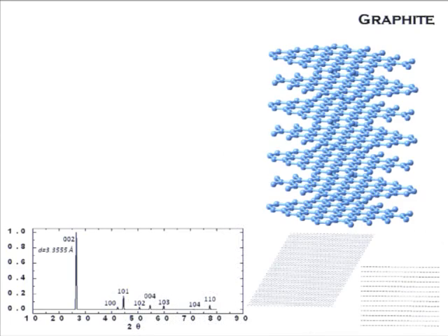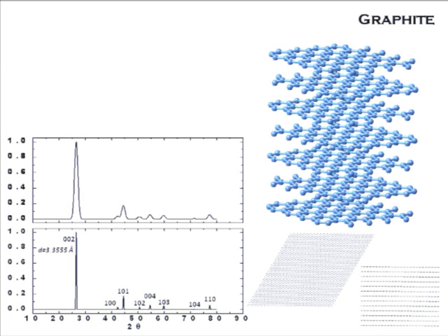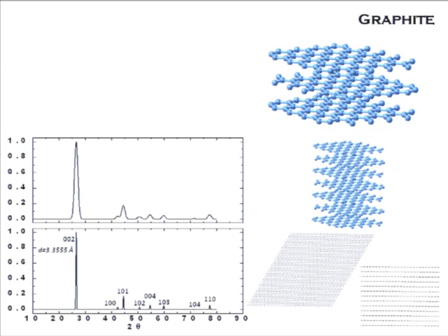And the diffraction pattern will be somewhat similar to what we had originally, but with broader peaks, and the peaks actually broadened anisotropically, which is hardly surprising, since this distance is greater than the distance perpendicular along the planes. Well, let's not stop here and try to mess up the structure even further. So let's cut it more, but let's not stop at that.